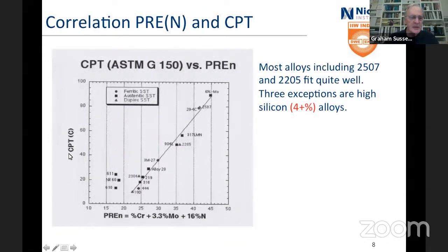This is looking at CPT, critical pitting temperature, versus the PRE. And as you can see, it's pretty much a straight line. And we've got super austenitic up there, we've got a super duplex there, we've got an ordinary duplex there, and a bundle of austenitics down here, and even, oh yes, there's another duplex there, 2304. So 2304, 2205, and 2507, all duplex stainlesses. The three exceptions for this, and you'll wonder why they're there, these alloys over here have much better corrosion resistance, but that's because they've got a lot of silicon in them, which does unfortunate things to their ductility, but it does improve their corrosion resistance.